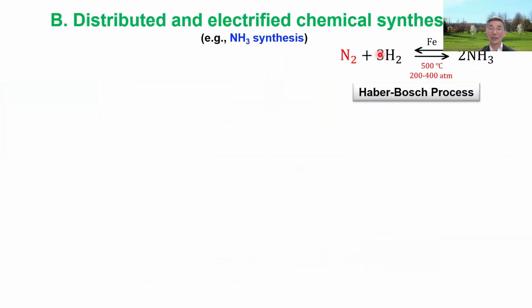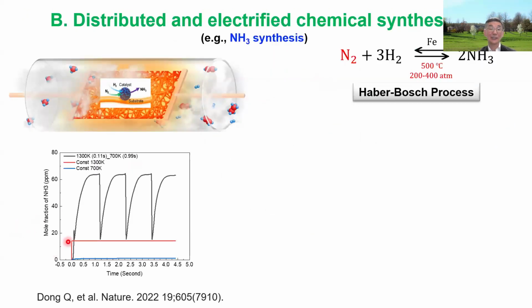Then we demonstrated another thing. Can we do this kind of reaction for ammonia synthesis? This reaction is the key; there are 2 to 3 Nobel Prizes in this reaction. It's an exothermic reaction, and it's very difficult to break the nitrogen bond. Therefore, you need a catalyst and a high temperature. But because it's also exothermic, you need a lower temperature. So with this heating and quenching idea, you heat it and quench it, heat it and quench it, shifting the equilibrium to the right-hand side. You can enhance ammonia synthesis.